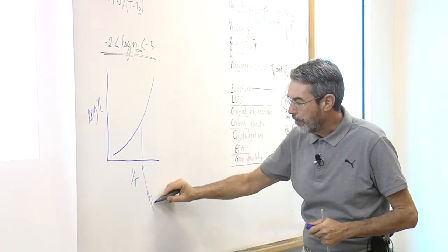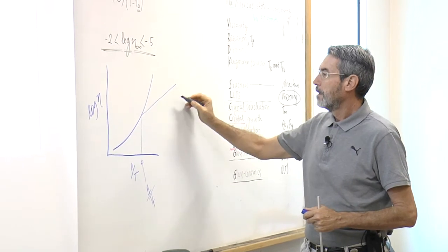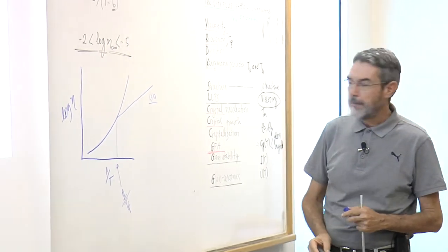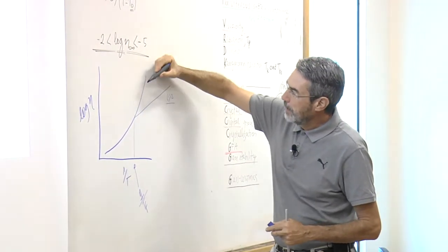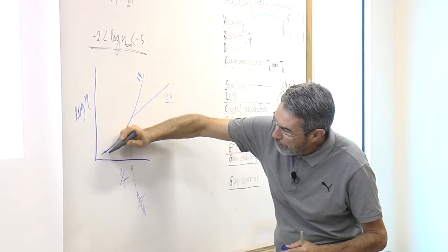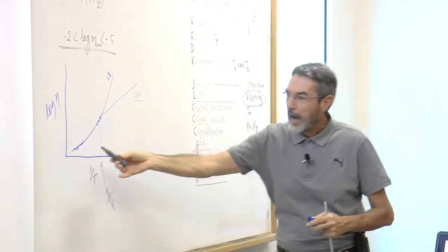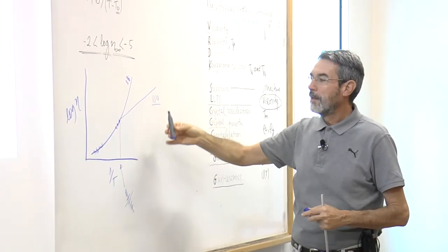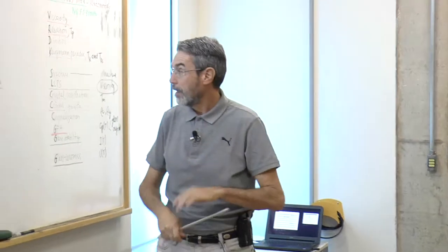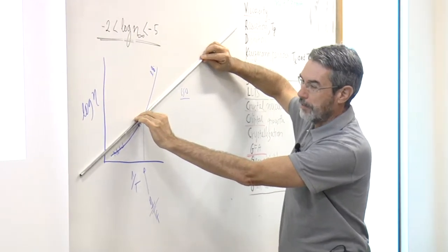Only at the so-called fictive temperature, which I'm going to explain in a minute, then below that, isostructural viscosity takes over. This is the equilibrium viscosity, and measurements are normally done here. Highly non-Arrhenian, then it becomes Arrhenian because the structure of the glass, of the liquid, is frozen, and then isostructural viscosity takes over.